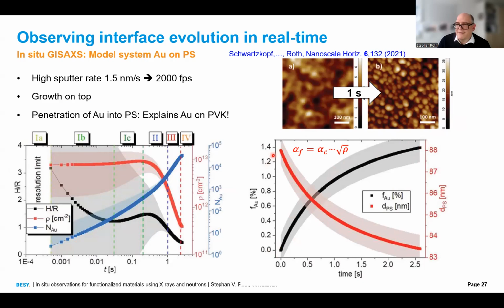We don't think they are clusters. From what we see as a growth mode or diffusion mode, it should be individual gold atoms which diffuse in. If it's 5 nanometers, it's essentially like 2 layers, or one, depending on material. But with a very, very low loading.